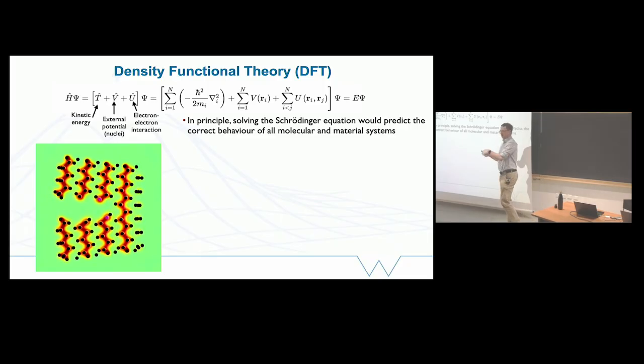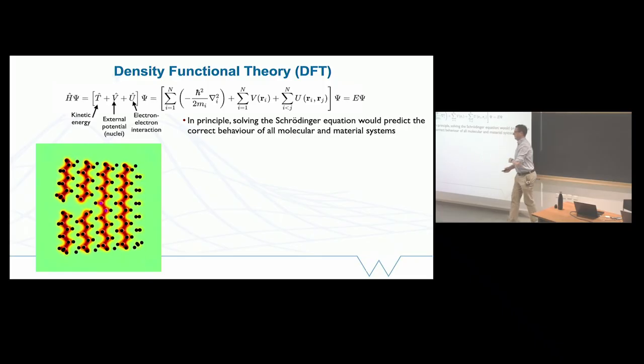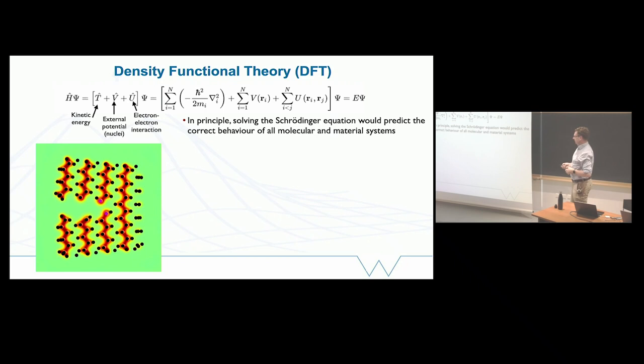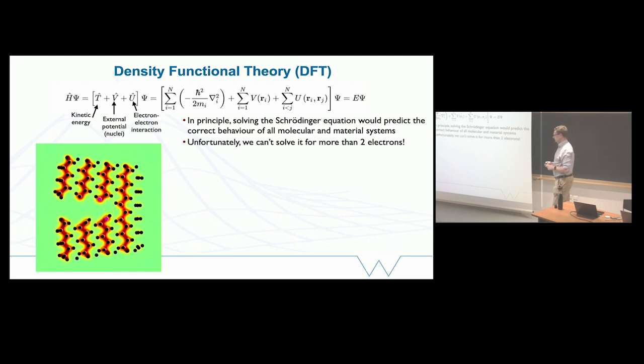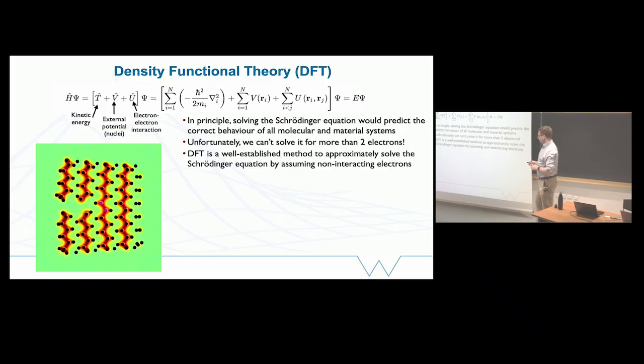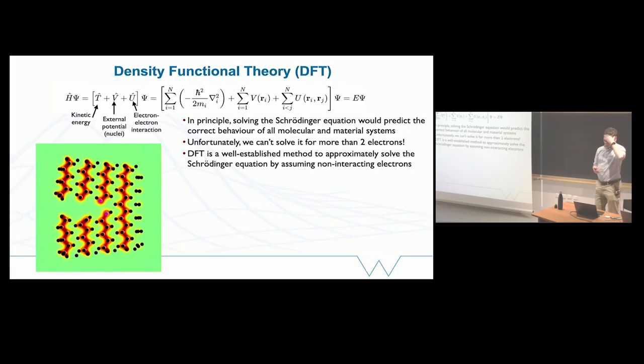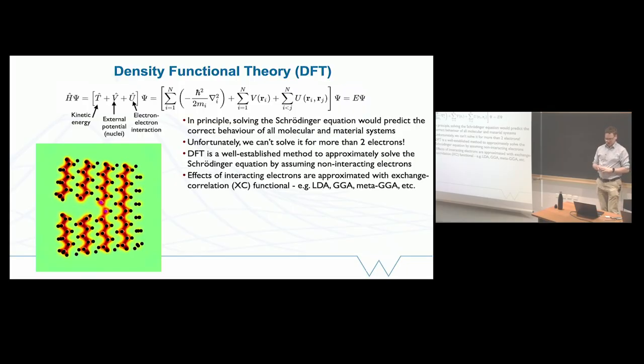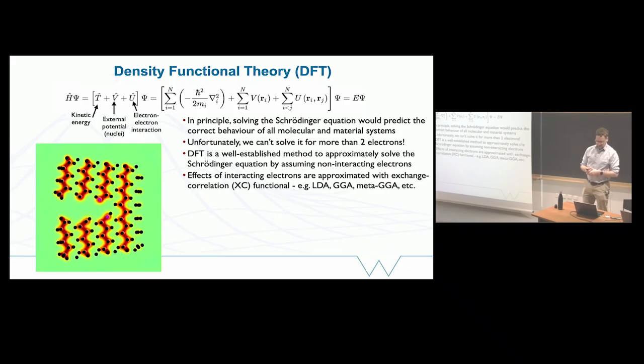So we put in all of the physics that we have, and then we have a part that describes the missing part. Unfortunately, we have to do that because we can't solve the full Schrödinger equation directly for realistic systems that contain more than a couple of electrons. So that's where DFT helps. It gives us this exchange correlation function that we put in where we model the electrons as non-interacting, and we instead incorporate an effective term to describe the interaction and the effects of exchange and correlation. So local density approximation, generalized gradient approximation, meta-GGA, etc.